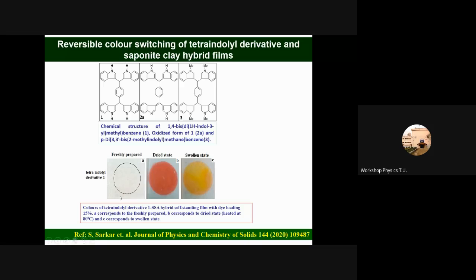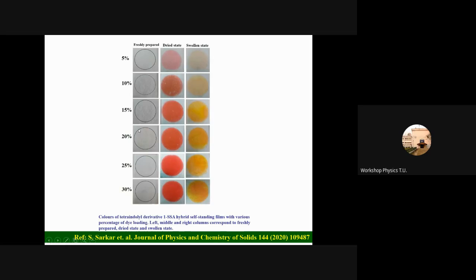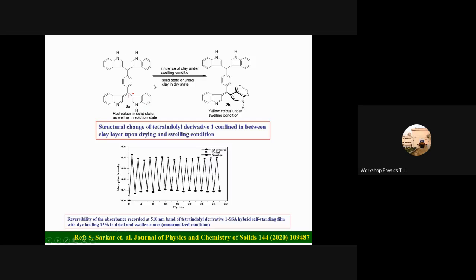This is another example, where we have shown an indolyl derivative and clay, and we prepared the film. You can see the prepared film is colorless, but when we heat it, it becomes red. Then when we swell it, it becomes yellow. And here it is shown for different concentrations. This is mainly because when we heat, oxidation occurs, color comes, the molecule becomes flattened, and pi conjugation becomes extended, accordingly a red color appears. But when it is swollen, some kind of twisting occurs in the molecule, accordingly conjugation is disturbed, and the color changes to yellow. And this is again reversible, possible using simultaneous drying and swelling.